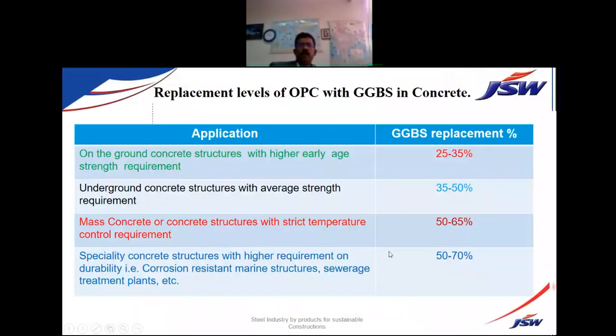So coming to the percentage usage, based on the applications, we can use this slag in concrete making, starting from above-ground structures where early strength is required, 25 to 35%. When we have underground structures, 35 to 50%. When you have mass concreting applications, about 50 to 65%, especially raft foundations, one meter above raft foundations.